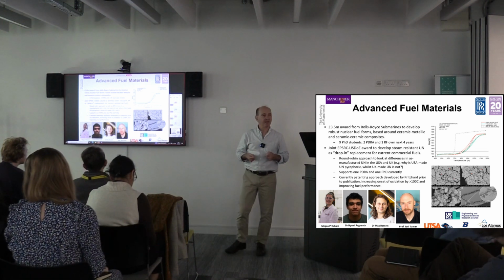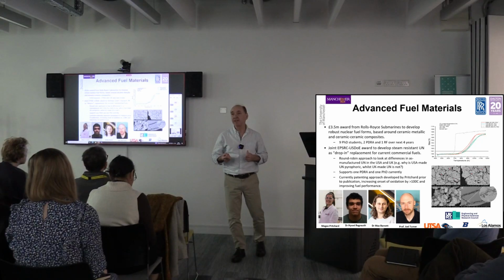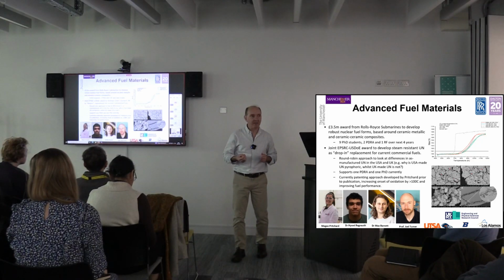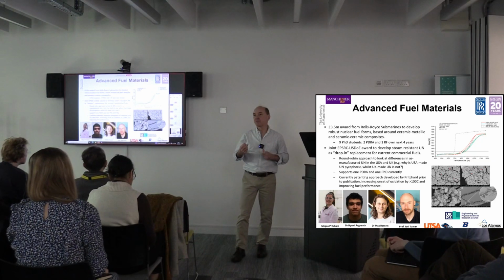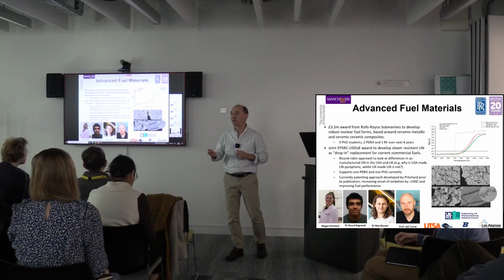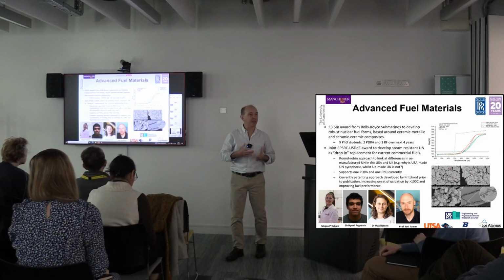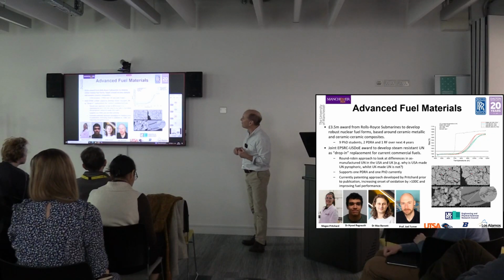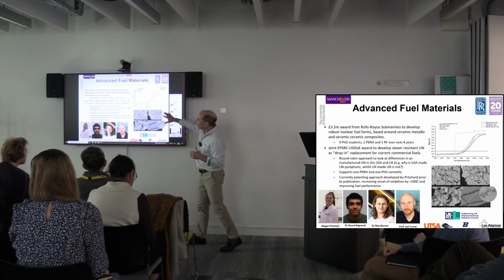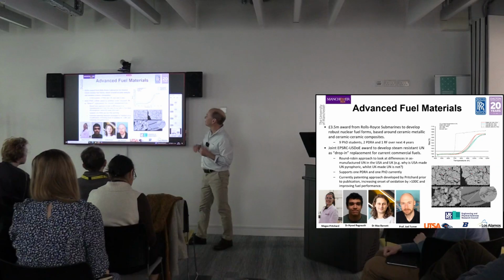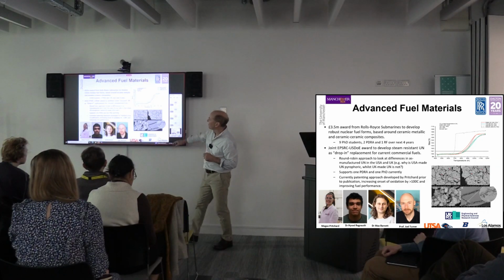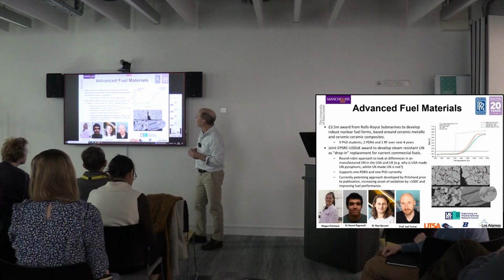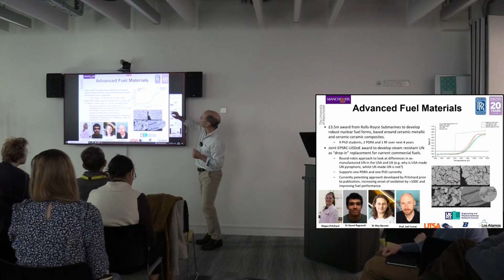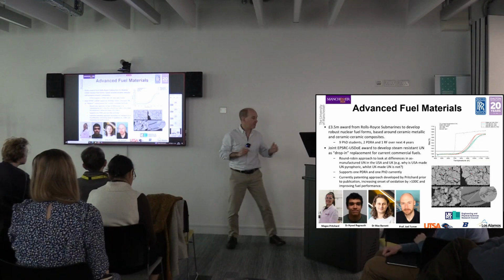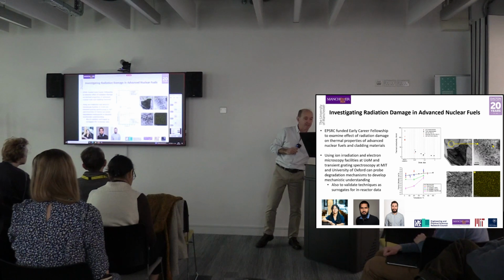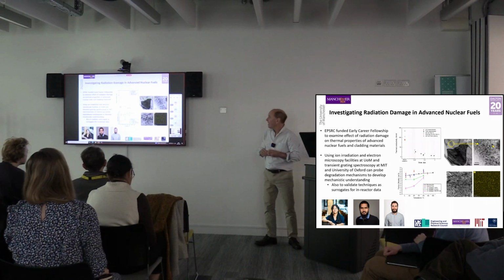rate than oxide does. So if we had a fuel failure in a water-cooled reactor, obviously we've got the possibility of water getting into the fuel rod and an energetic reaction taking place between the fuel material and the water. So we think we've got some potential solutions to that. One of them is currently being patented at the moment, but we've got a lot of work taking place on advanced fuel materials, at the moment centred around nitrides.